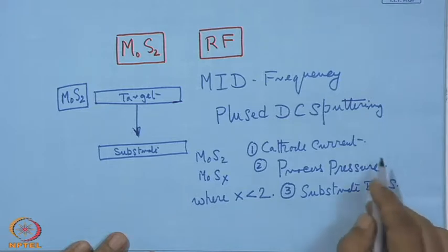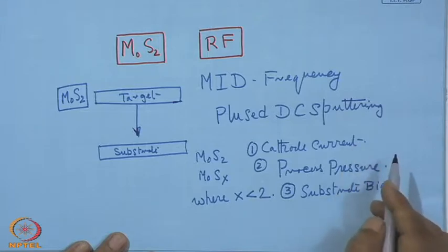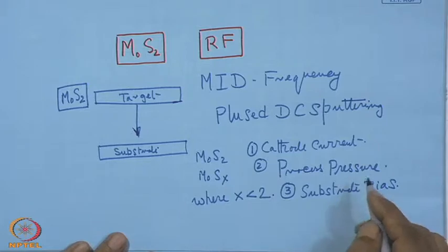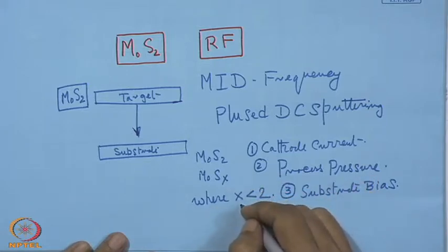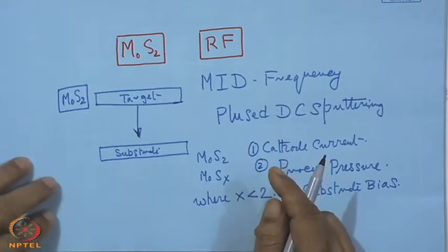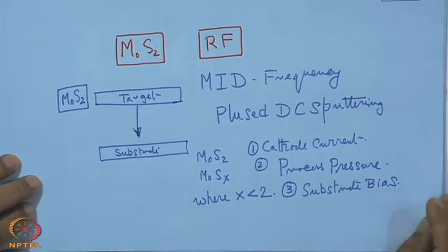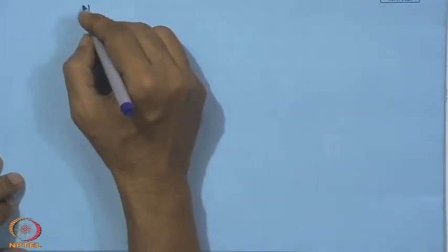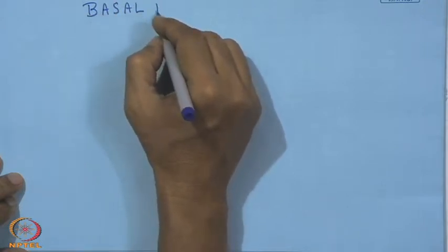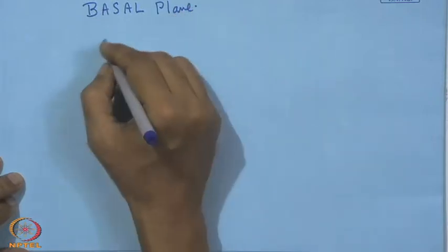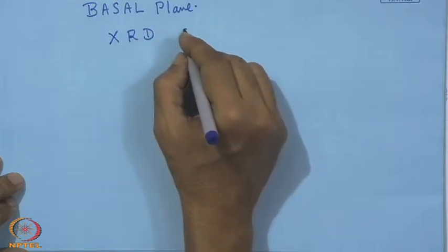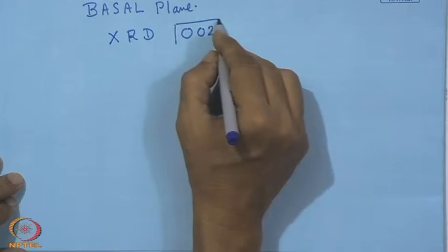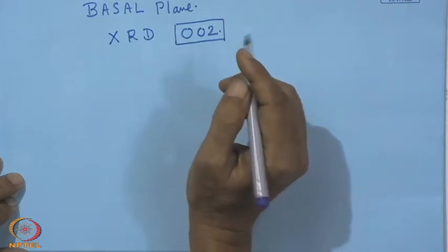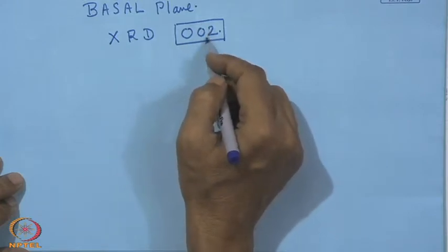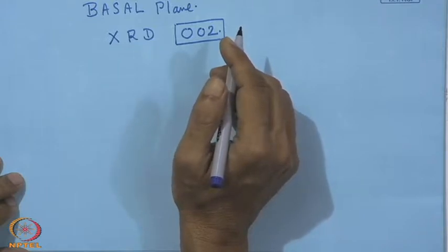substrate bias. So, this combination of these 3 is very important; their selection and their combined effect can lead to a particular value of x, and not only that, it can also determine the formation of the basal plane or edge plane. So, this is what we can mention here. When it is the basal plane, from the XRD, X-ray diffraction diagram, we get a peak of 002, and that is a confirmation of the existence of the basal plane, which is given by this 002 orientation, and that is parallel to the substrate surface.